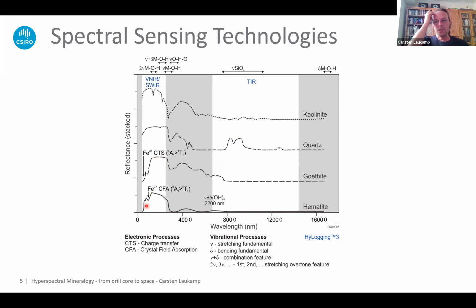With iron oxides, the visible near infrared is really important because they are full of iron. So you've got all these absorption features related to iron here, ferric iron charge transfer and crystal field absorptions. There are also absorption features here in the longer wavelengths in the far infrared, but it's really difficult in natural samples to make sense out of these things. We're doing lots of comparisons with natural samples, like collected with the NVCL, comparing those ones with single crystals and literature about single crystals, and it's just a different world. Yeah, you can nicely identify or discriminate different goethite and hematite species or ilmenite in the far infrared, but in a natural sample, good luck.